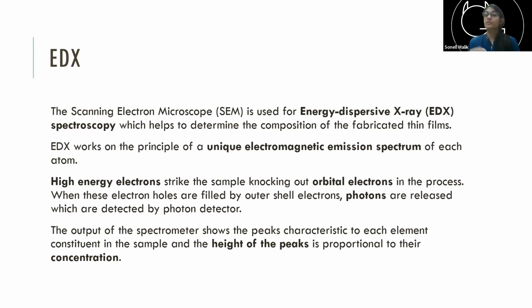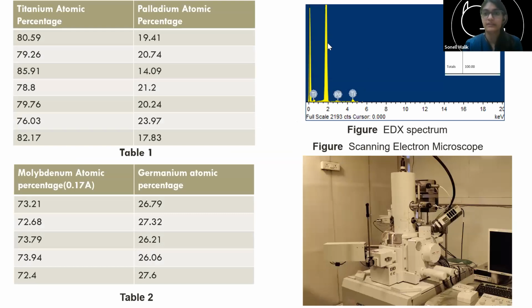Based on the number of photons you get for each energy, you can also figure out the concentration of the material that is present in your sample. That's how you get this diagram here.